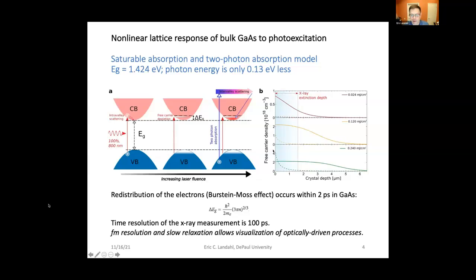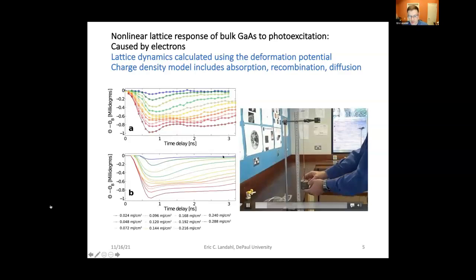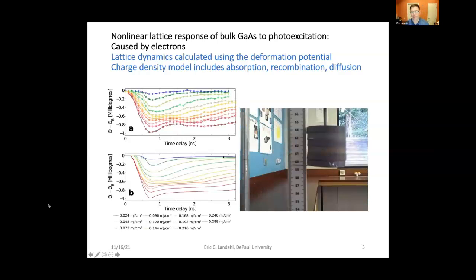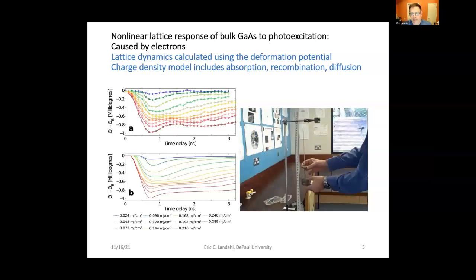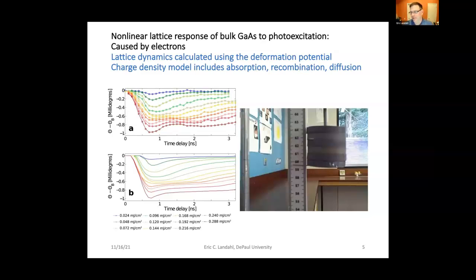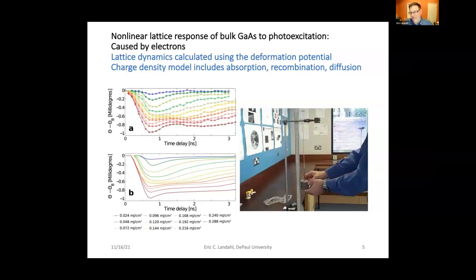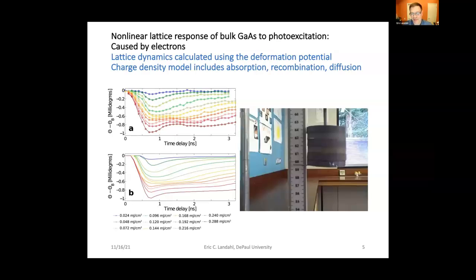something else starts to happen, which we ascribe to two-photon absorption and an increasingly non-uniform, shown here in the dashed green line, absorption of the laser light. To quantify the model a little bit, as you go to nonlinear strains in the mechanical system, you start to see some strange time behaviors. Shown here, you see with the elastic band, slowly the mass falling a little bit after it's actually put on.